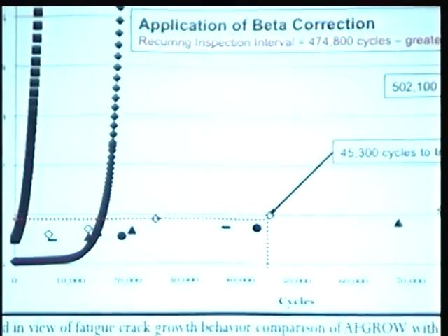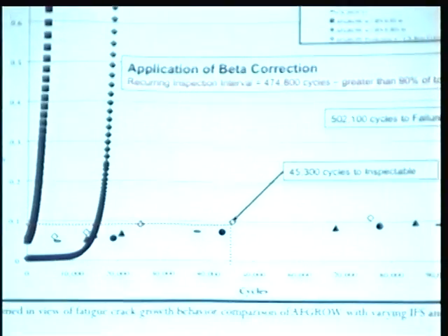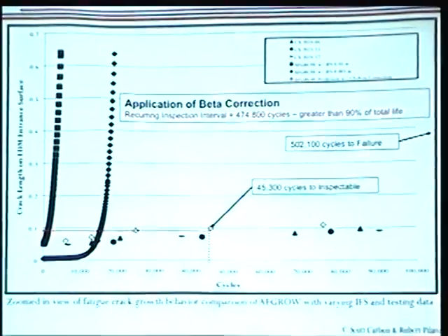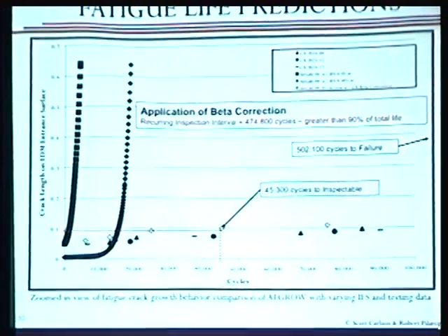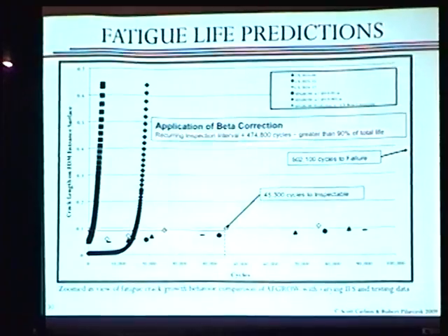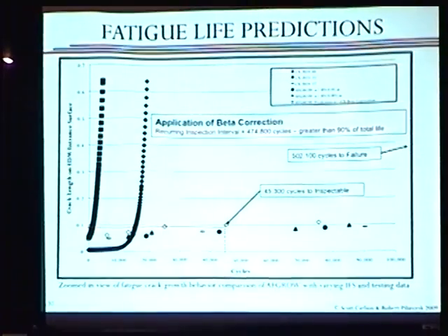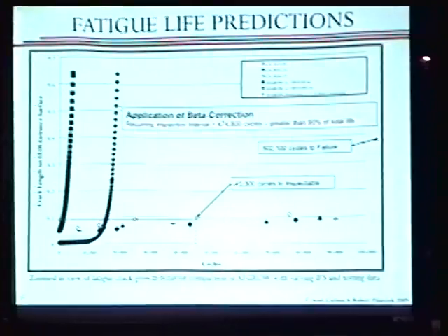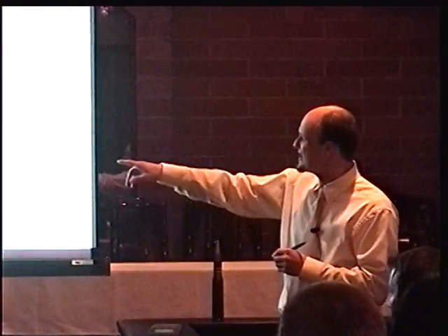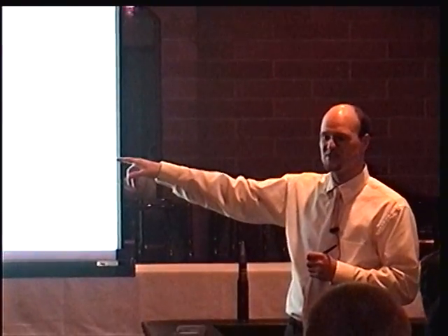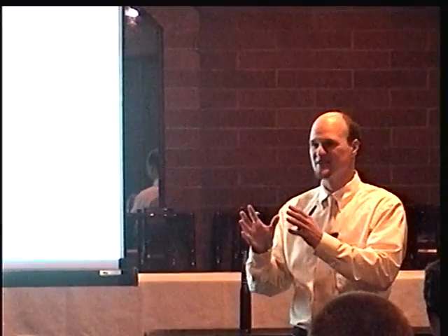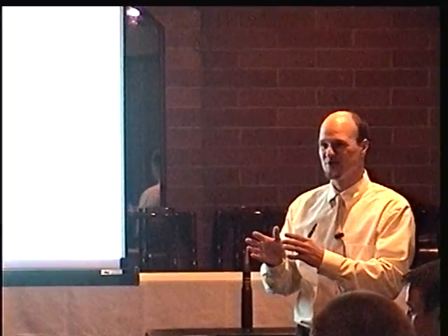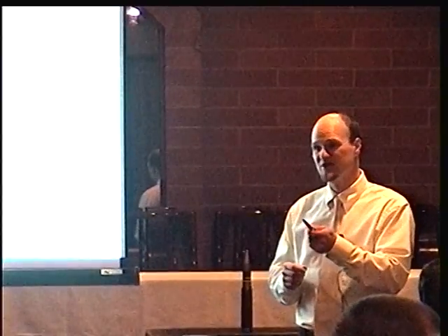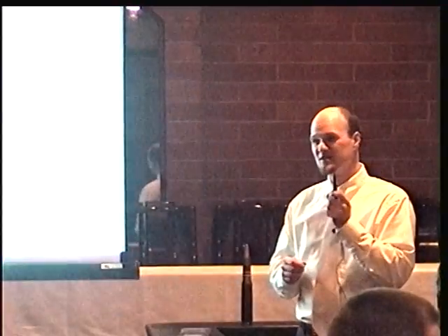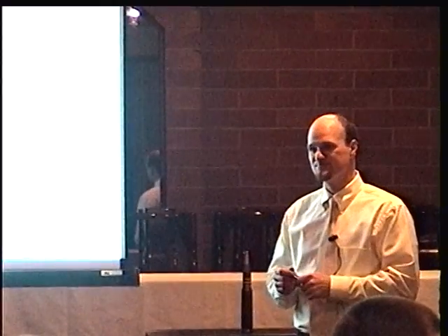And the nice thing about it is, because of the behavior of the cracks at cold expanded holes, it's kind of unique because the maximum residual stress is a little bit away from the hole. The free edge is no stress. So you've got to get into the component a little bit to really feel the effects. So what happens is the crack actually starts to propagate similar to what you would see in a normal specimen, but then it hits this area of high residual stress and just shuts down for a long time. So that's good from an NDI point of view because it's at a detectable flaw size for a long time.